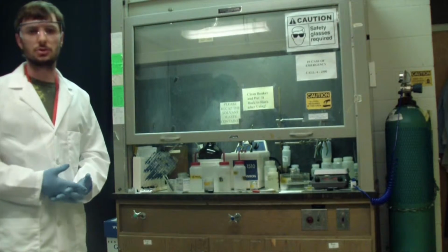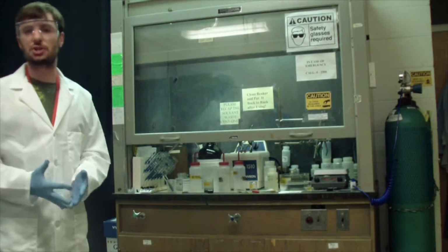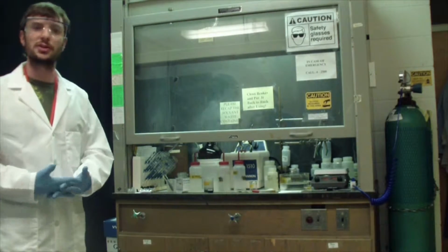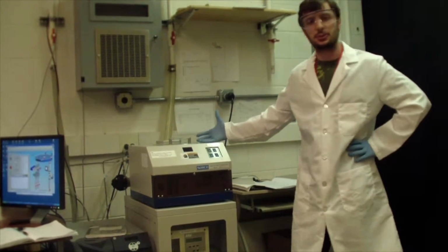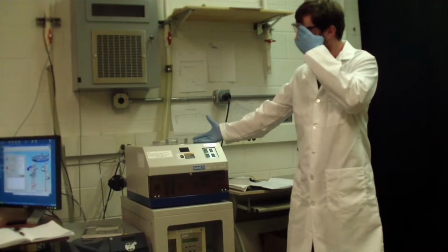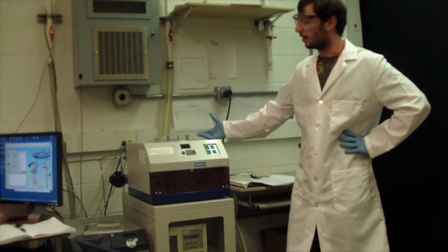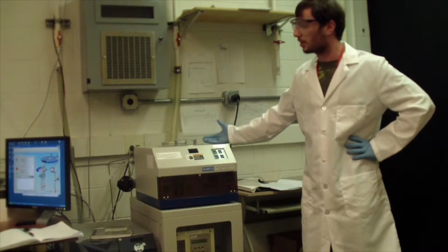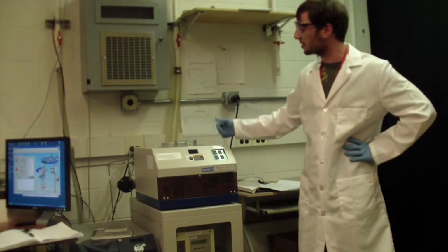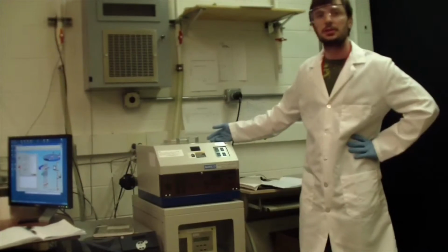and then IPA to finish the cleaning of the samples. In the fabrication of nanostructures, we do lithography. Ion etching system. We create a plasma inside. Plasma is an ionized gas. And the main use we have for this in graphene is to do a plasma of oxygen. With oxygen, with carbon, it chemically reacts and forms CO2. So we're able to etch structures of graphene by putting a mask on it and then exposing it to the oxygen plasma. And we can reach really, really small features using the technique.